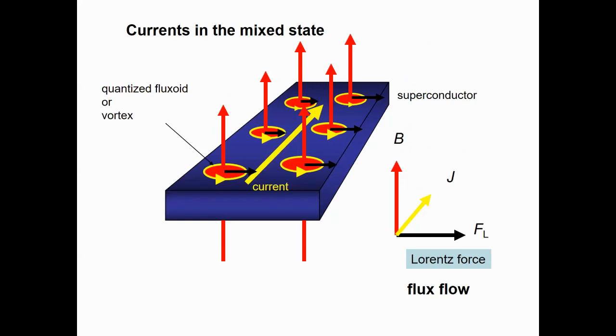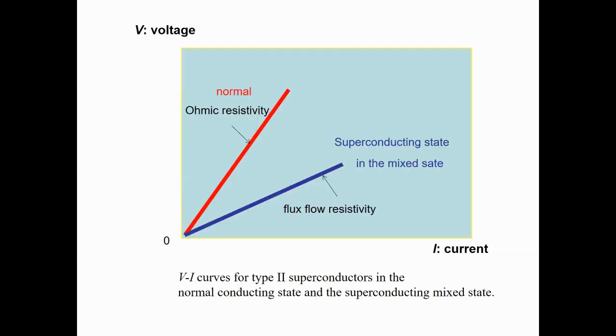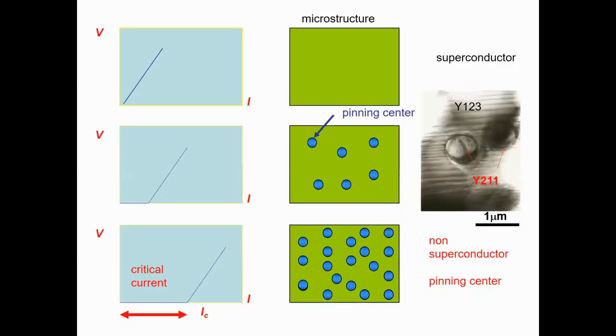But there was another problem. If we pass current in the mixed state, the Lorentz force acts on the fluxoid, the quantized magnetic field, or vortex. And lots of normal conducting electrons are there. So if the fluxoid moves, then resistivity appears. We call it flux flow resistivity. So in the case of a type 2 superconductor in the mixed state, we cannot achieve zero resistivity because of flux flow. So we have to stop flux motion to realize zero resistivity.